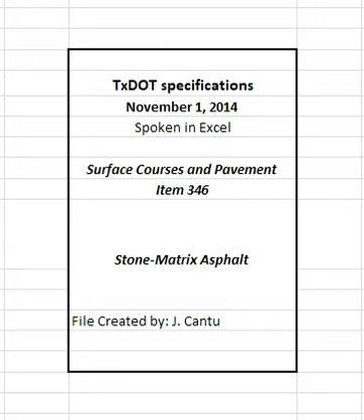Visually inspect each core and verify that the current paving layer is bonded to the underlying layer. Take corrective action if an adequate bond does not exist between the current and underlying layer to ensure that an adequate bond will be achieved during subsequent placement operations. Trim the cores immediately after obtaining the cores from the roadway in accordance with Tex-207-F if the core heights meet the minimum untrimmed value listed in Table 10. Trim the cores on site in the presence of the engineer.